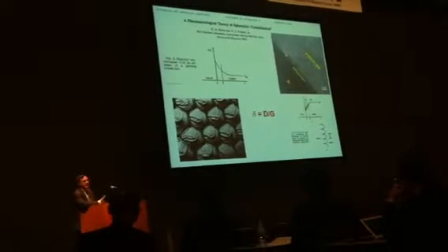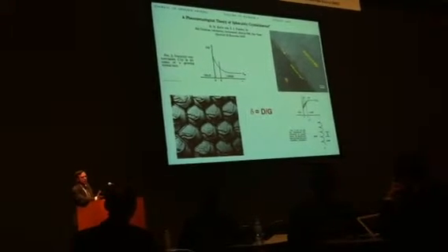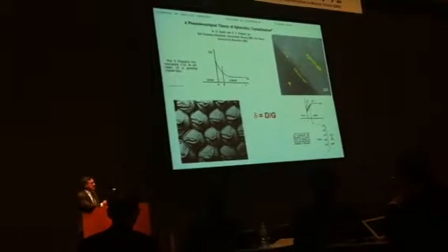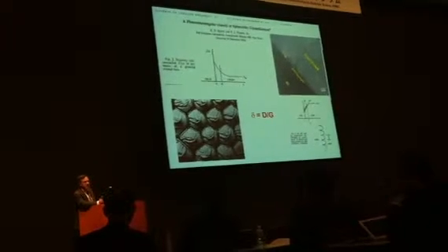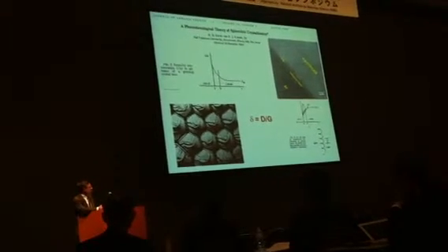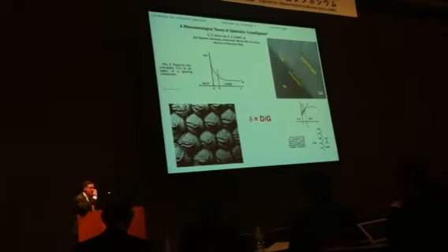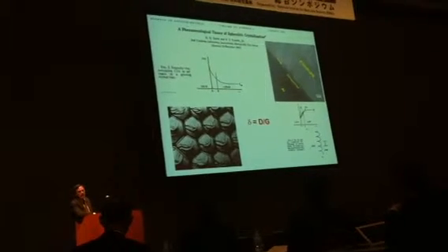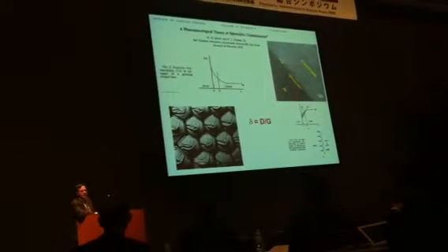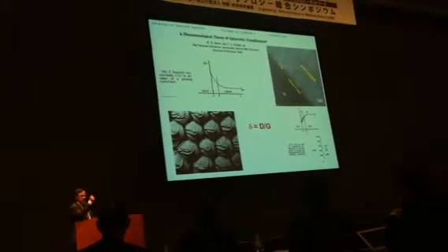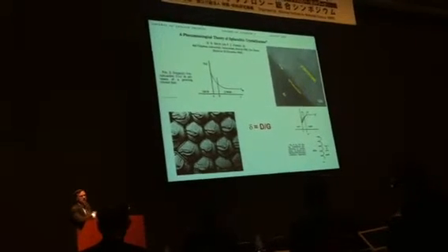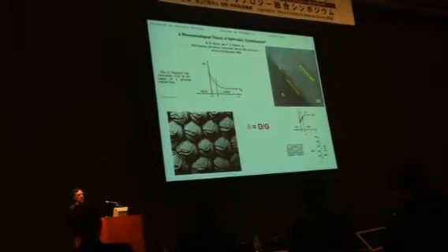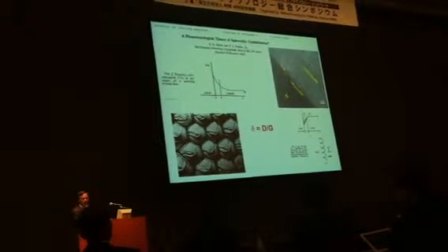Now the reason behind this is a very simple, classic polymer physics problem. If I take a mixture and one component will crystallize, you nucleate the crystal, and the crystal front will grow. The crystal front grows, but it is pushing the non-crystallizable material out of the way. And that happens to be the PCBM. So we have the nucleation density, which is of importance, and then we have the growth rate of the polymer crystal and the diffusion coefficient of the impurity, PCBM, away from this interface.